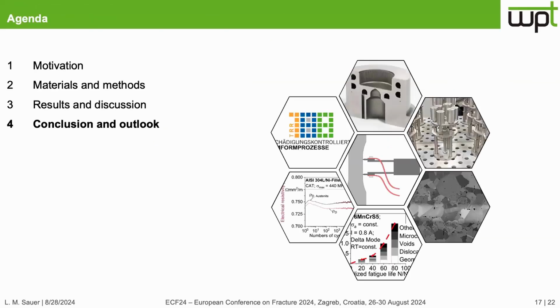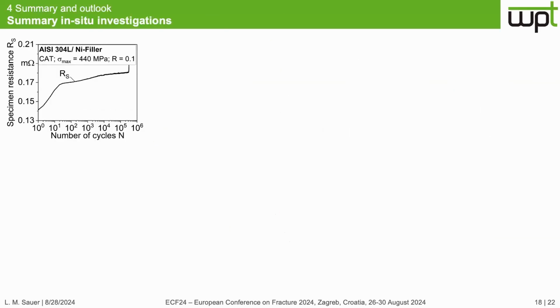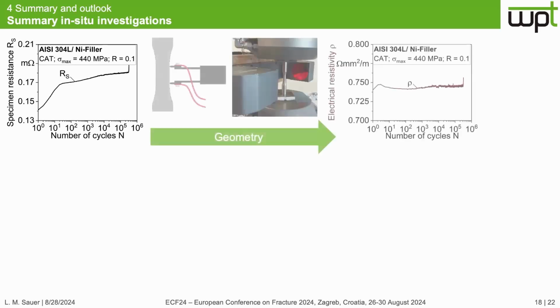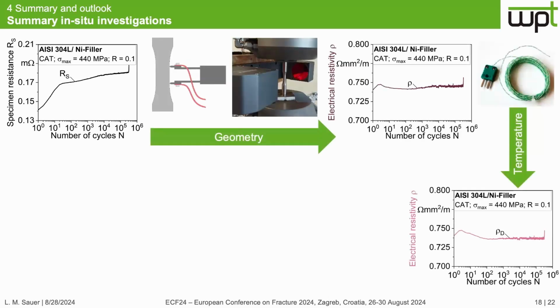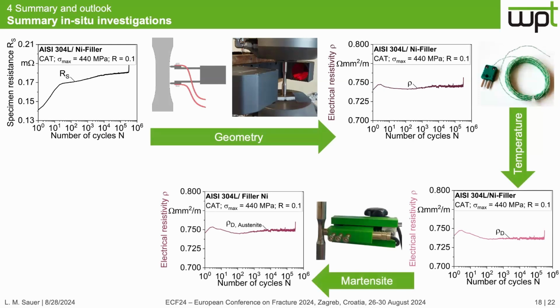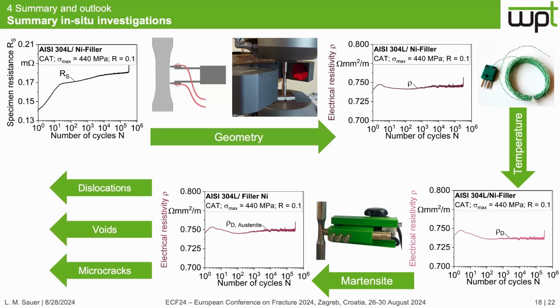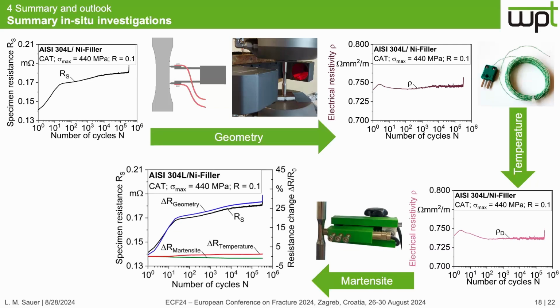And I will now come to the conclusion and outlook. Starting with the electrical resistance, the influence of geometry, temperature, and martensite was compensated so that the temperature-independent electrical resistivity of the austenite was determined, which no longer depends on geometry, temperature, and martensite transformation, so that the microstructural changes can be evaluated, but it's not yet possible to separate between them.